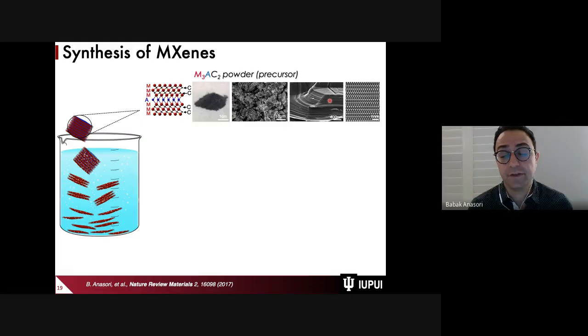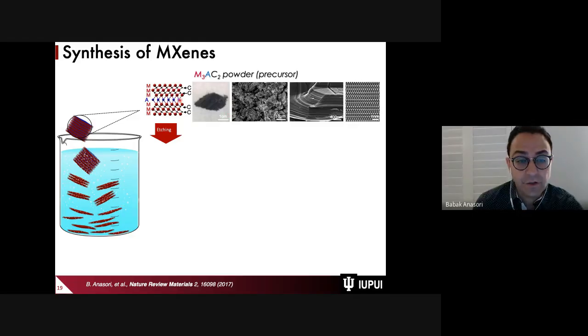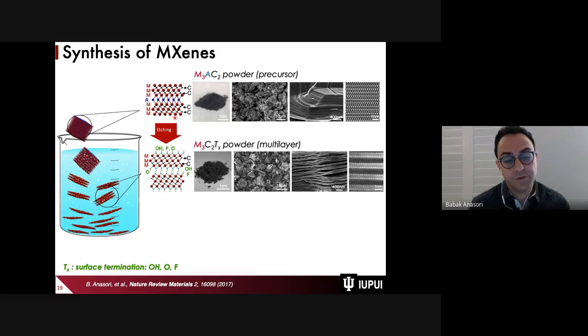With a closer look under scanning electron microscopy, we see that it has a layered structure. Going even further down by using high resolution scanning transmission electron microscopy, we see the atomic layers here. Then we put it into the etchant, which is mostly hydrofluoric acid or something that forms hydrofluoric acid, for example, a mixture of hydrochloric acid with lithium fluoride salt. It etches selectively only certain layers. By removing aluminum from the structure, we get another grayish powder, but this time, instead of this bulk structure, we see a more open structure. Even at the atomic level, we see that they're all open, which means we have openings between the layers. And that's where we get to the two-dimensional.